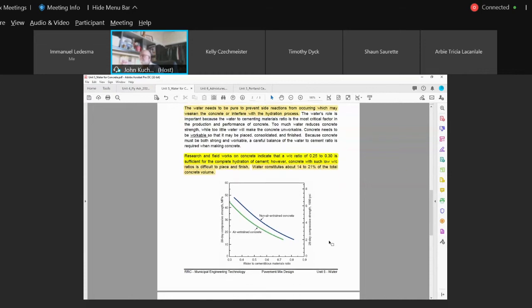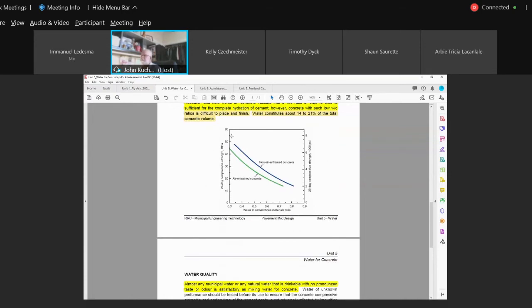Hint, okay? And here again, you can see this is just a relationship between the water cement ratio and 28-day strength. Okay, you can see air entrained concrete and non-air entrained concrete. And right off the bat, you can see that at a certain water cement ratio, non-air entrained concrete gives you better strength. But for the inside floor slab, you don't need it for freeze-thaw durability because there is none. But maybe you can't finish it as well. So even a lot of designers will use air entrained concrete for inside because of finishability. It's easier to finish air entrained concrete than non-air entrained concrete.